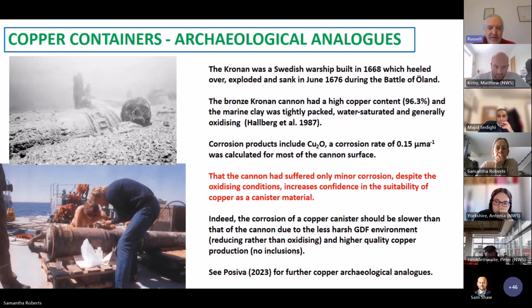back in the mid-80s, they found that in general, even those which are sitting here, you see with the skull in the top picture, have only suffered minor corrosion despite the oxidizing conditions in the water. At slight depths in the sediment and clay, obviously it went anoxic. But it has been used, especially by SKB, as one of their arguments for the suitability of copper as a canister material. The recent POSIVA study at the bottom there, 2023, has a lot more examples of copper archaeological analogues, which if you're interested, you can have a look at. The Kronan cannon is on show in a museum in Stockholm now.